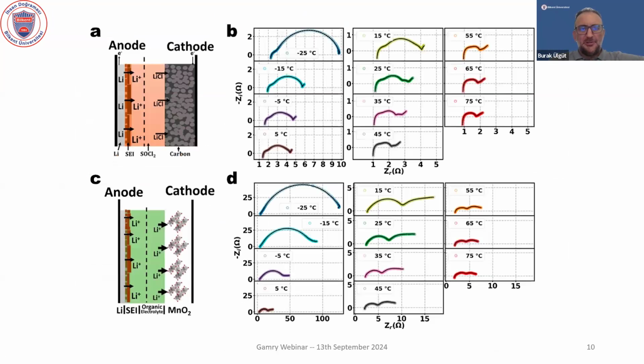So here I'm showing two separate sets of data from two separate batteries. On top, I have a lithium thionyl chloride battery. This is a battery that I've worked on quite a bit because it's fascinating. You can get 19 amp hours on a small lantern size battery, so D type for the Europeans. It is primary, so it's not rechargeable. It has a lithium metal anode. But the defense industry uses it quite a bit because 19 amp hours in D size is something that you cannot beat. The reason you can get that much energy density is because the solvent for the electrolyte, the SOCl2 on that figure, is also the cathode active material. That's what gets reduced. So you can see that the solvent and the cathode active material are the same, so it saves a lot of weight, and that's why you can get a lot of energy out of it.